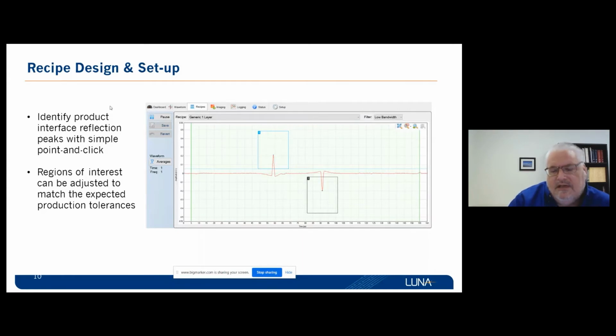Our instruments essentially have this very sophisticated software that allows you to set up this waveform analysis that can happen either 100 times per second or 1,000 times per second, depending on the waveform acquisition rates. But we have industry-leading waveform window lengths where we're acquiring the greatest range, which works out to, say, in the air from up to about 4 inches worth of depth. Although the working distance can be longer, the window is centered on about 4 inches. And then waveform acquisition up to 1,000 times per second.